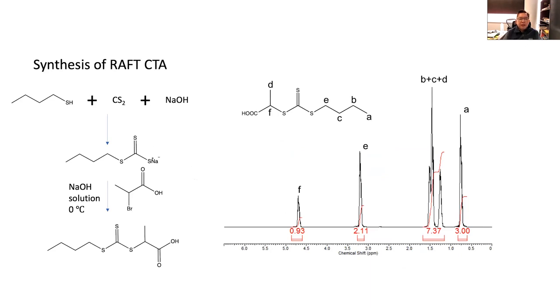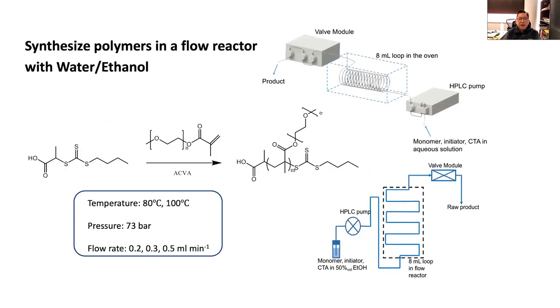So first we synthesize here, shown by NMR, the chain transfer agent based on this thioester, and then we loaded this on the column together with the monomer, PEG methacrylate, and the ACVA or AIBN analog, which again is an initiator for free radical polymerization. But in this case, since we are using a controlled pressure, we can increase the temperature and therefore achieve a shorter half lifetime for the initiator, and therefore the reaction can be carried out in minutes rather than hours. Again, another savings for doing things in the laboratory under flow.